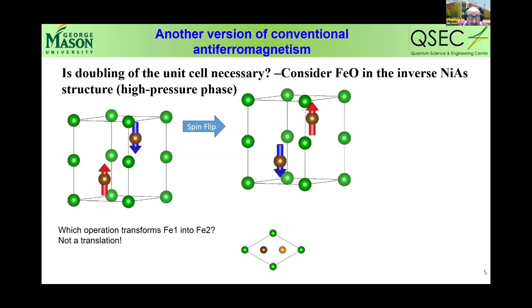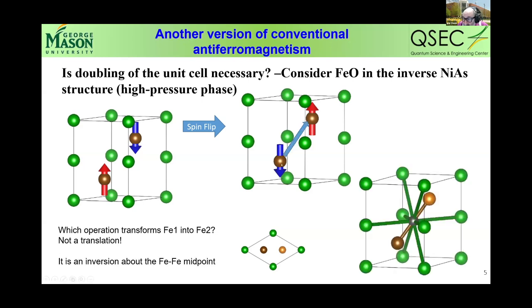There is a symmetry operation because both these iron atoms belong to the same, what we call in crystallography, Wyckoff orbit. That means that there is a symmetry operation that maps one onto the other. In this particular case, it's not, of course, translation, it's actually inversion. Here I illustrate it very clearly. This is the inversion center, this gray ball, and you can clearly see that the inversion operation maps all green atoms upon themselves, and at the same time maps one iron onto the other iron.